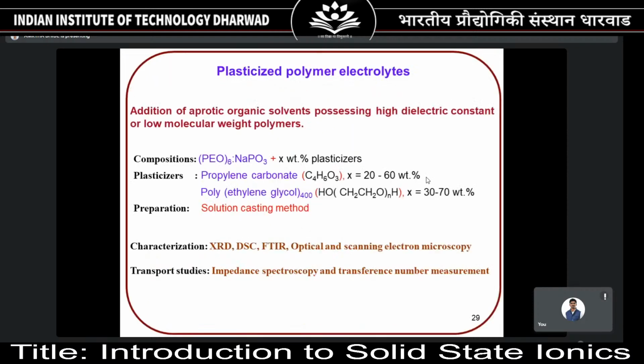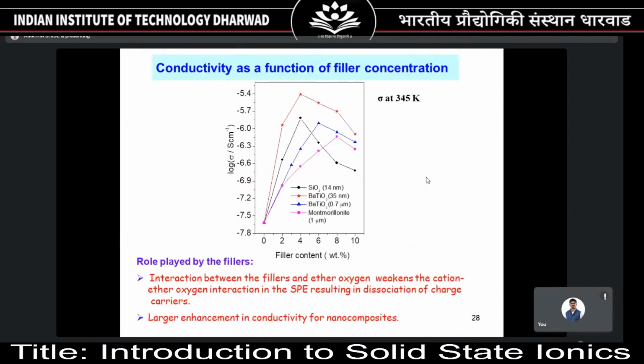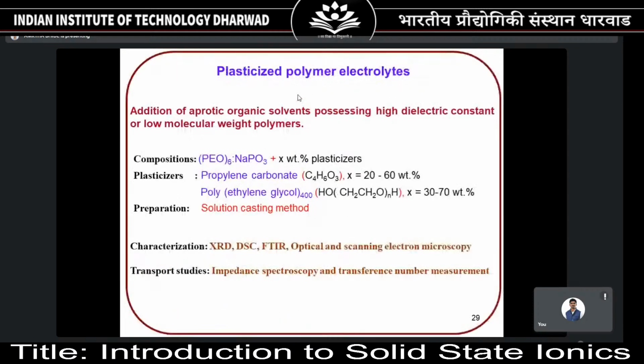And then there is one more category, that is plasticized polymer electrolyte. Here, before coming to this, you could notice that the solid polymer electrolyte which we had earlier was showing conductivity of the order of -8 at 78 degrees Celsius, and now it has increased by 2 orders. Now there is another way of enhancing the conductivity, that is plasticizing the polymer electrolyte.